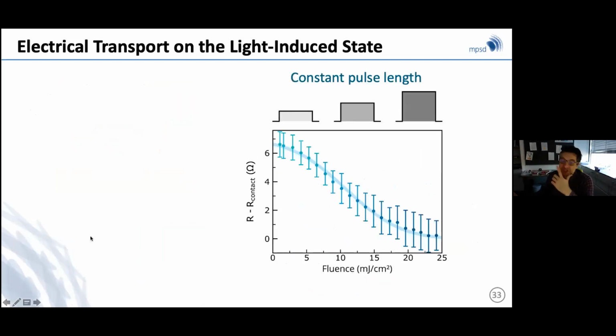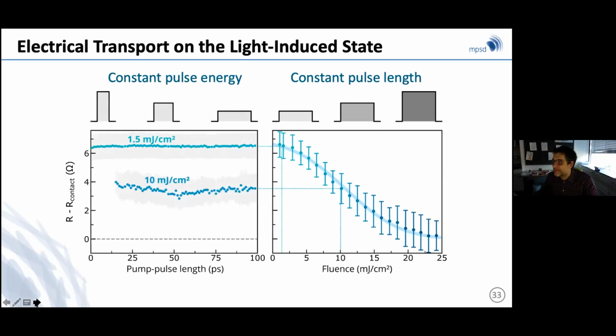So what's very interesting, which is an effect that we did not predict, was that if you plot this resistance as a function of fluence, what you can do is you can basically change either the pulse duration and reduce the intensity and maintain the area, or keep the duration short and increase the intensity. But be as it may, what we find is that the light-induced state is only dependent on the total energy inside this pulse. So basically the area of the pulse determines your ability to turn the state into a zero resistance state.